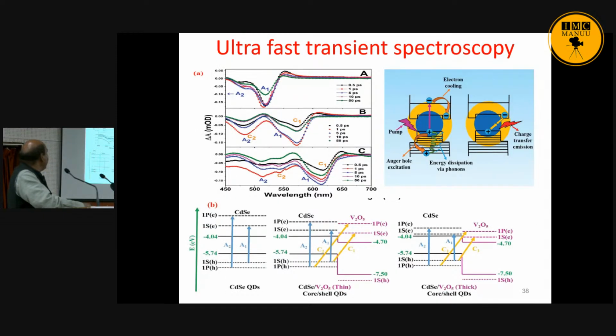Then we did ultrafast transient spectroscopy in the NPL. If you see, CdSe is showing a single dip. But CdSe/V2O5 is showing double. CdSe is showing the direct transition, while CdSe/V2O5 is showing direct as well as indirect transition. So we conclude that the electron cooling rate decreases here with CdSe/V2O5. If the electron cooling rate decreases, such a material can be useful for photovoltaic applications. So CdSe/V2O5 is also useful for photovoltaic applications.